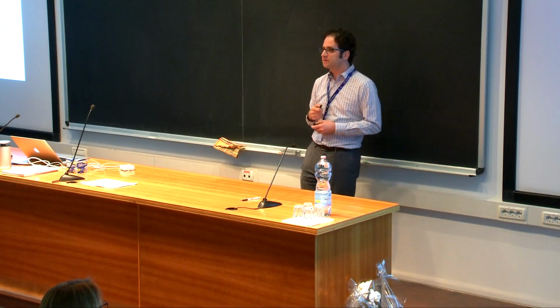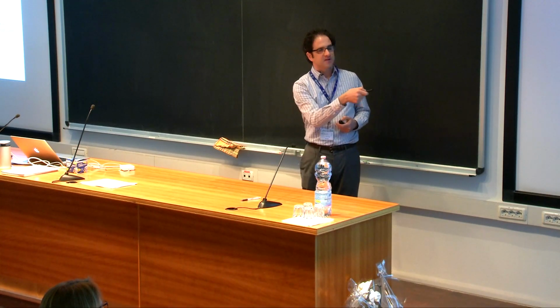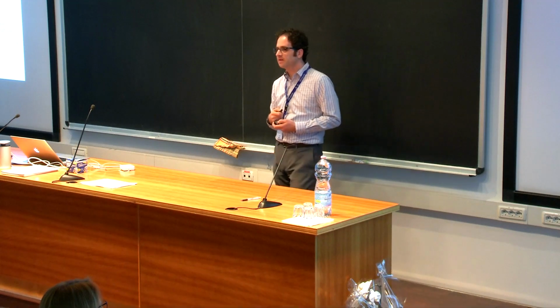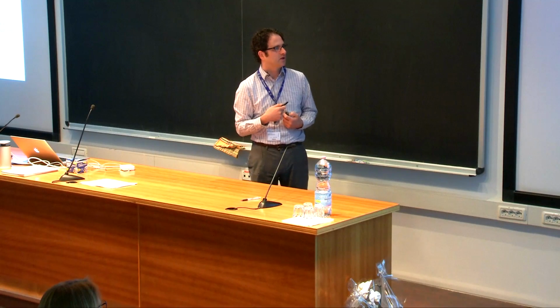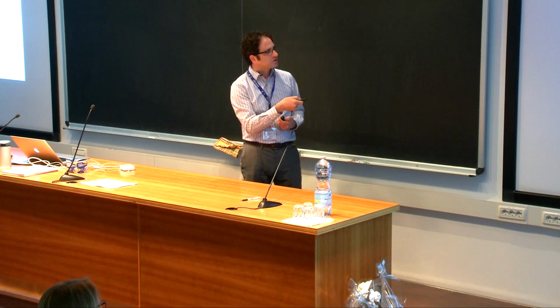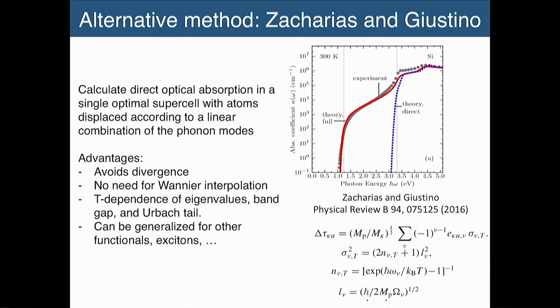The previous equations have this problem that if your intermediate state becomes real, then the equations diverge, and you have to incorporate somehow the lifetime of those states to avoid it. It also avoids the interpolation, and also gives you the temperature dependence of the eigenvalues and the band gaps, as well as this long Urbach tail at long wavelengths.